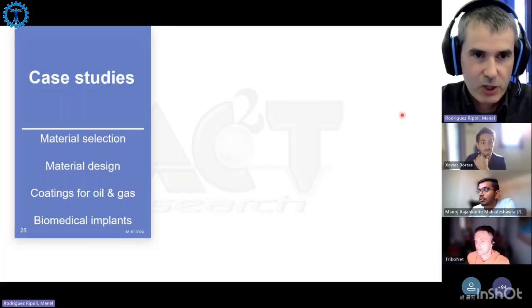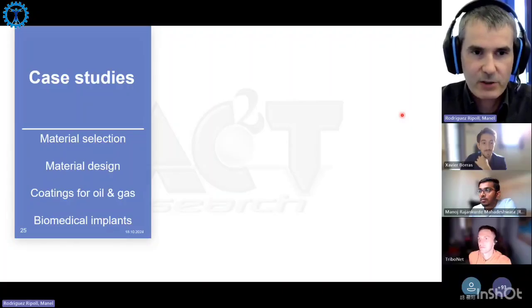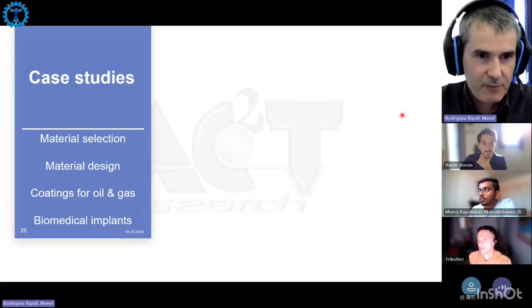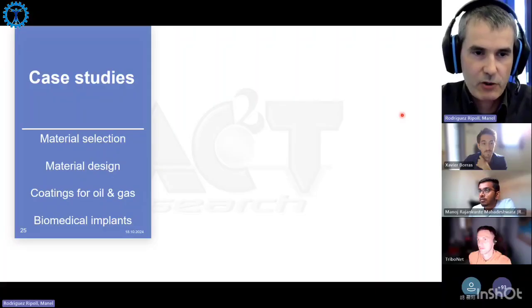applications. So one possibility, for example, is to have a material that has different kinetics. For example, chromium nitride is a material that also, due to the repassivation kinetics of the material, is very suitable for tribocorrosion applications, and chromium nitride coatings perform much better when compared to titanium nitride under tribocorrosion. So you can use different materials, but the tricky point here is that you cannot rely on pure corrosion or pure wear experiments to determine which of these materials is going to be the most effective for tribocorrosion protection. Thank you for the answer.